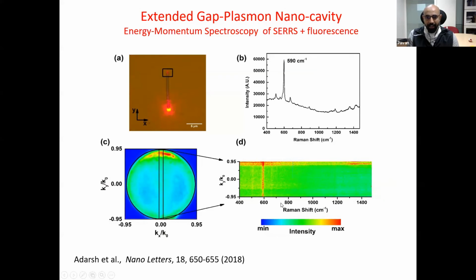So what you find is a very interesting thing. It tells you that the Raman scatter signature is now confined to a large wave vector distribution, whereas an electronic process like fluorescence or photoluminescence is mainly confined to the small wave vectors, and this gives some kind of differential scattering processes, which can be utilized for very confined light matter interactions.